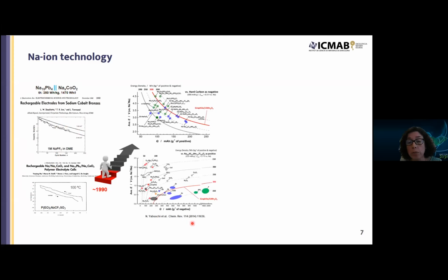And here you see, from a review back in 2014, all the compounds which had been shown to be useful as positive or negative electrodes for sodium ion batteries, and an estimation of the energy density of full cells using those materials as positive electrodes and hard carbon as the negative one, and comparison with graphite, LiMn2O4 lithium ion. And you see that in some cases one will have competitive figures of merit. And the same is the complementary graph, thinking of different negative electrode materials versus a layered oxide as positive, and again, comparison with lithium ion.